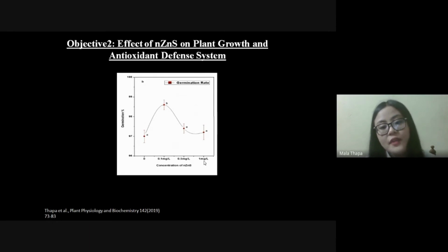Now, entry of ions inside the seed is a tough task because of the hard coat of the seed. But in case of nanoparticle, due to its tiny size, it can easily enter into the seed through water transport movement and enhance the seed germination. Again, nanoparticle can form pores which can facilitate the nutrient uptake inside the plant. So, in our study, zinc sulfide nanoparticle treatment significantly increased seed germination in treated seeds.